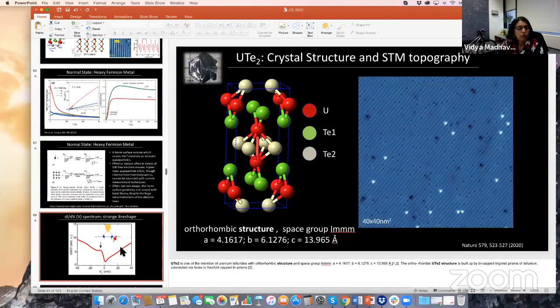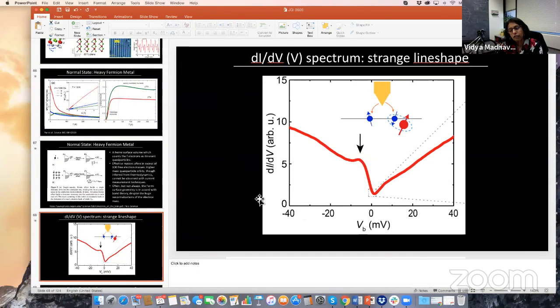When you take a large energy spectrum, you see this feature right at zero bias. This is actually a signature of a heavy fermion. This is like a Kondo resonance. So this is a very high density of states, very close to the Fermi energy, because of this heavy fermion band that comes up below the coherence temperature.